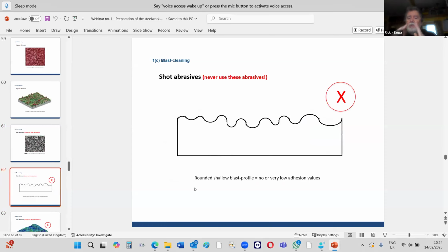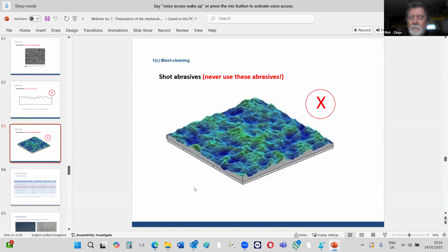You have no lateral support. So if you have a shear, if something hits that surface, it's going to rip off all the zinc, because there's nothing to anchor it deep inside the metal. It's just like a golf ball almost, very, very smooth. And there's a 3D image from a computer. There are no deep valleys. If you look around the outside edges, they're all round and scalloped. There are no deep V's. So that's very, very bad.